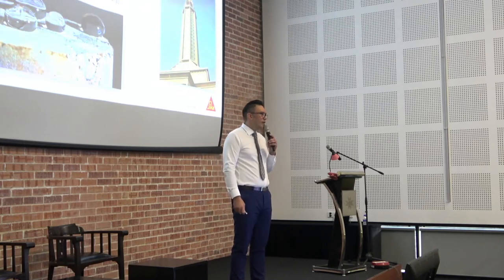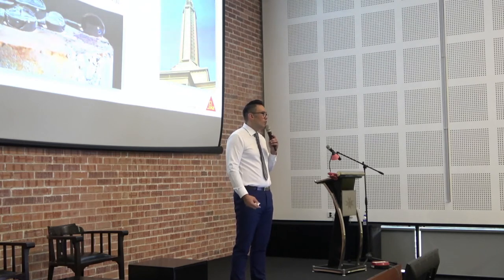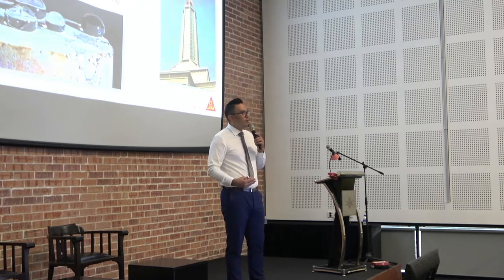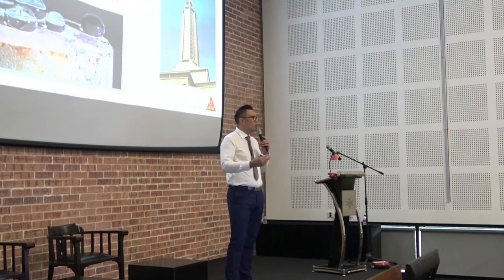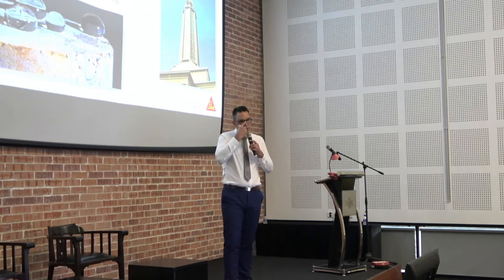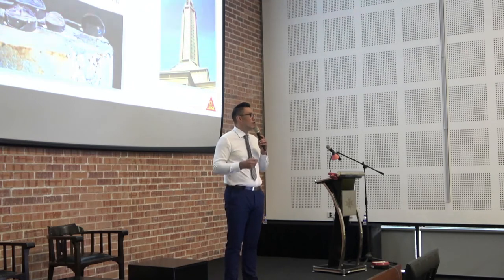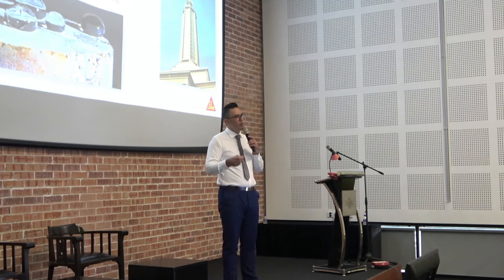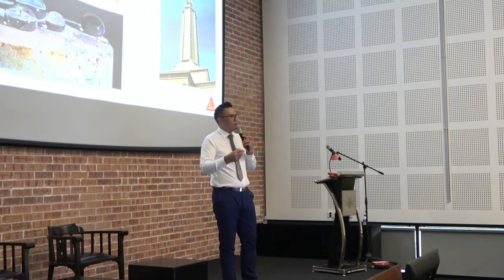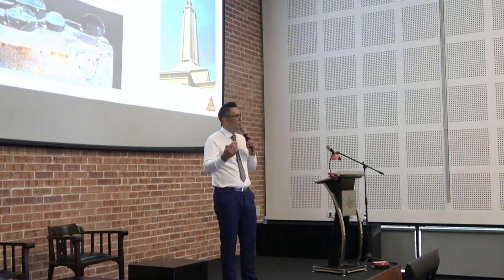It's fairly easy to apply once you have access and once you have a good method in place. It can be either rolled, sprayed, brushed on. And what's important is the porosity. We need to check that you get good uptake and that you get the right amount of product or the right amount of active content onto the surface so that it can penetrate it.